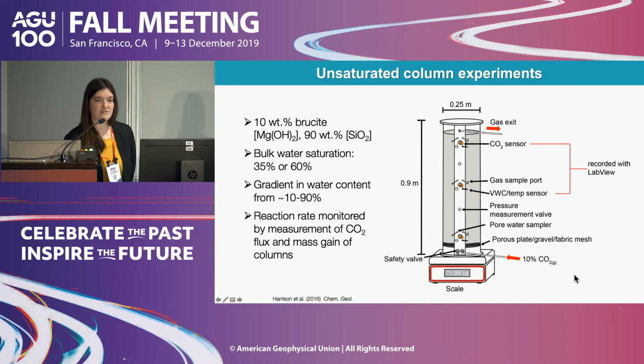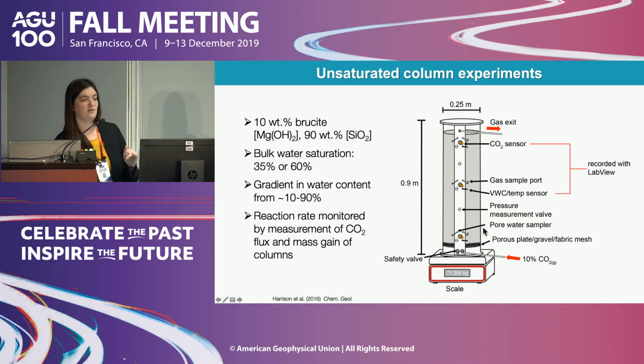We supplied a CO2-rich gas at 10% CO2 that flowed in through the base of the columns and exited at the top. We could track the reaction by having these CO2 sensors along the flow path, which monitored the removal of CO2 from the gas phase into the mineral phase. And we could also excavate these columns afterwards and observe where minerals had formed and how much carbonate had formed with depth.